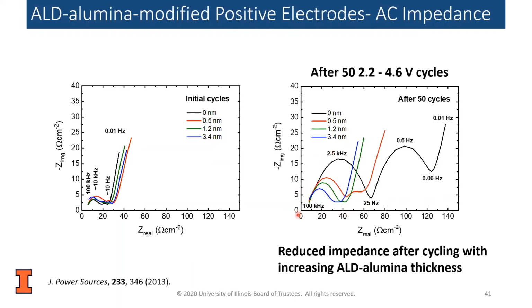And so if you notice right here, this is a good example of that double semicircular behavior. And this lower semicircle indicates that we think we're beginning to break down the electrical network of the system. And that is, we're beginning to coat the graphite and the carbon black. So now we're not able to shuttle those electrons from the oxide particle to the current collector. And so now this system is no longer very useful as a battery. So this battery would be pretty much used up.